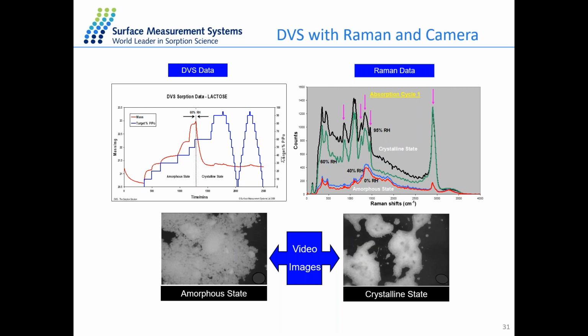And with the DVS method, we can also detect the amorphous content inside the material with some special methods. If we have reference data and a certain humidity vapor that can induce this kind of phase change, we can then detect how much amorphous content is inside the material. The DVS method is proven to be a very accurate and reproducible method to detect this kind of amorphous content. We can detect as low as 0.2% amorphous content in the material, still with very good reproducibility.